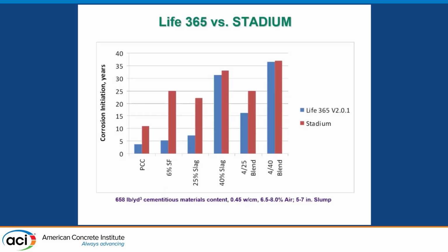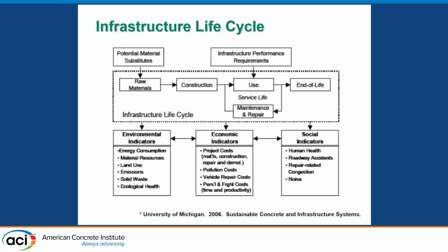And again, here we compared the Life-365 to the STADIUM program. We see that there are a few differences here. So STADIUM is in the red and the Life-365. We do see that Life-365 treated things a little bit nicer at times, which is good, but very similar at the 4 and 40 blend and also at the 40% slag blend. And again, we think some of it needs a closer look at the data. But certainly, the point I want to get across here is that what you put in is what you get out. And it has implications.